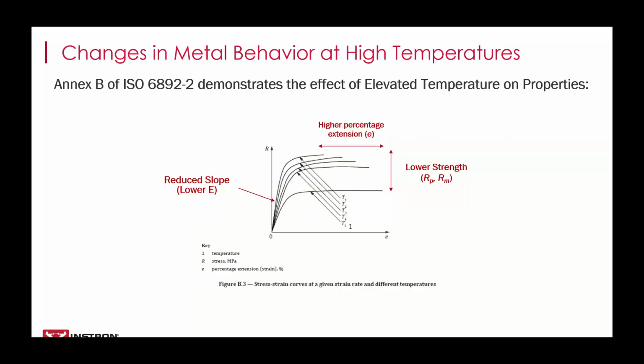Now, Annex B of ISO 6892-2 provides some terrific visuals of how materials behave differently at high temperatures. In this first figure, we consider 5 tests of the same alloy as measured at increasing temperatures. Like I mentioned on the last slide, the slope of the elastic region starts to flatten out as the material has less stiffness. The higher the temperature, the greater the atomic distance, and the weaker the forces between the atoms. So less force is needed to stretch the atoms out.